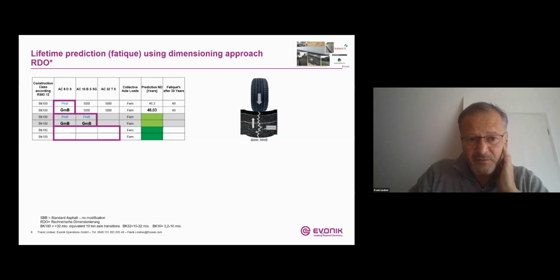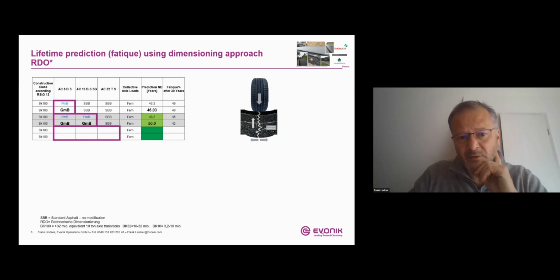But it changes if you go down and add also the modification of the binder layer, and you have already modified your top layer. And you can see that a longer lifetime can be expected by the use of rubber. And if you do the full modification of the asphalt package, like we see it now, then you see a significant improvement of lifetime on the side of the rubberized asphalt.